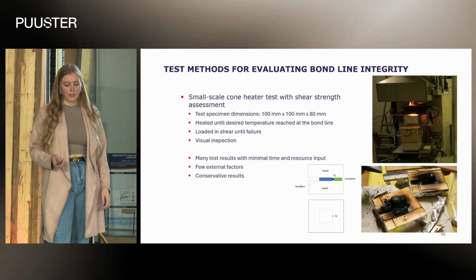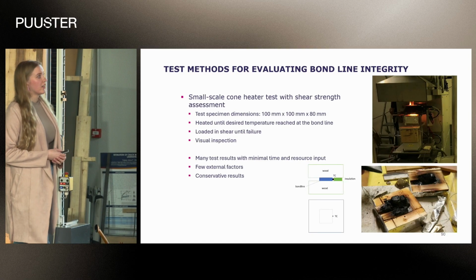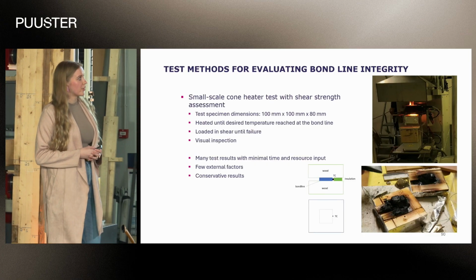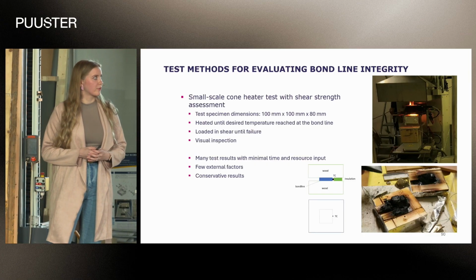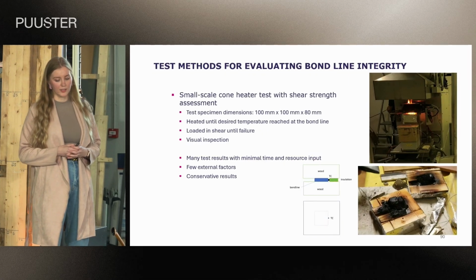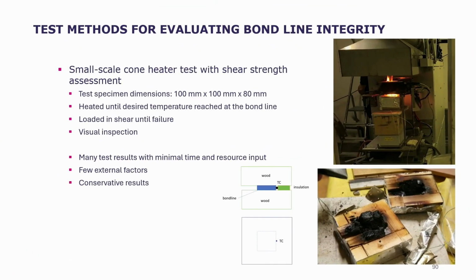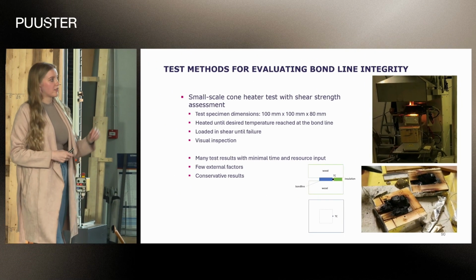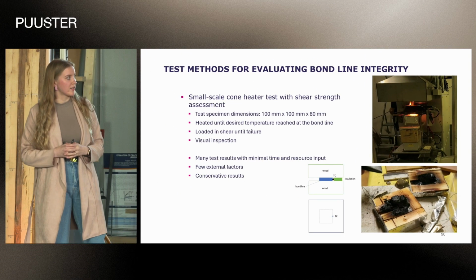And then we have been developing, here and in Europe in general, small-scale test methods for evaluating the bond line integrity. The first two of the three have been developed here at TalTech. The first one is a small-scale cone heater test with shear strength assessment. So we take a specimen about this size, heat it until the temperatures in the bond line reach what we want. Typically it's 290 degrees.